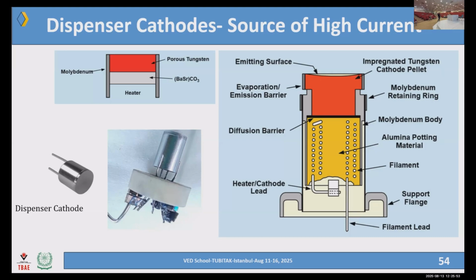You first have to go through the vacuuming, and then you go to the conditioning. Conditioning means the slow heating of this device, and then it should work. When it is meant to be exposed to air or stored, what we do is we purge our system with nitrogen or any inert gas, because then the monolayer which is formed is not poisonous. Of course, we have to go through the activation cycle again, but that activation cycle is less extensive if the exposure has been to nitrogen.